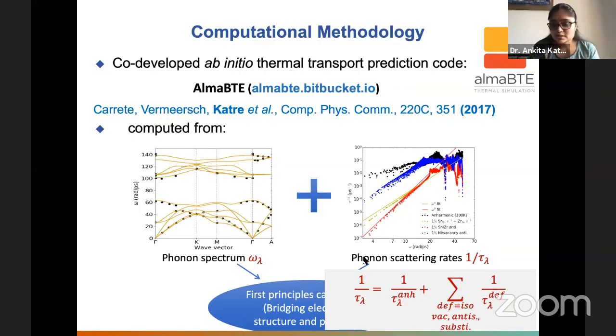These contributions include, as you see, the anharmonic scattering, which means the phonon interactions are taken into account. And if we are talking about point defects, atomic defects in the material, which I have studied as of now, we have to take care of different defects which could be present. Isotopes could be there, vacancies, antisites, substitutions, and so on. Depending on the samples and the synthesis process, as well as deliberate doping, we have to include the role of all those defects in the total scattering rate to calculate the final thermal conductivity.